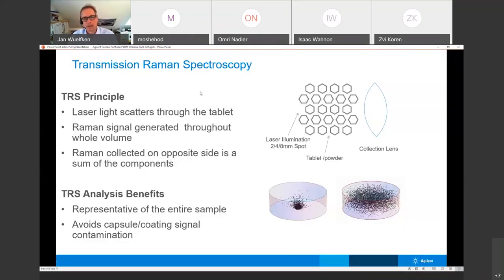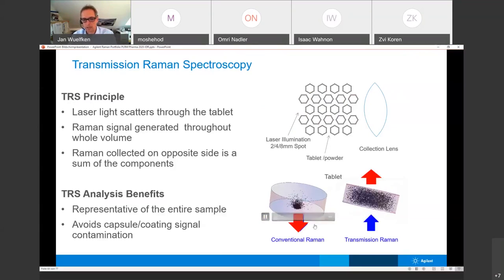So if you like, the laser scatters through the tablet. So it goes in the surface, and because the laser is finding its way, if you like, through the tablet, we have the collecting lens and it goes to the detector. And this is because it goes through the whole volume, and you can see this underneath here. This is why it is much more sensitive than any backscattering or traditional laser, because the traditional Raman systems, the backscattering type, are just measuring a bit of the surface and of course a bit inside. We are measuring everything. This is why we are so sensitive and we can do what we can do.